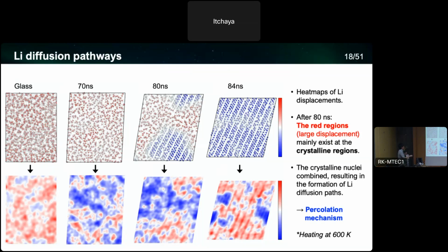As you can see in the glass, the heat map is quite, I'd say, uniform. But when the annealing proceeded, the uniformity decreased. And at 80 or 84 nanosecond, if you compare the upper and lower panels, we can see the red region, which is the high, fast lithium migration region, almost completely matched with the crystalline region. So in these calculations, what we found is that the enhanced ionic conductivity is mainly because of the precipitated crystalline phases, which is the alpha phase.